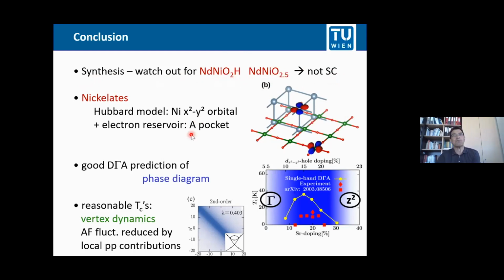Then I've shown you that for the nickelates, you can effectively describe them by a one-band Hubbard model for the nickel x squared minus y squared orbital. The A pocket is just an electron reservoir, a passive bystander that comes out from DMFT calculations with multi-orbitals taken into account. And then as a next step, at least in the blue region of doping, you are good with a one-band Hubbard model. We calculated the phase diagram, and the Tc is very good compared to experiment, even though we did the calculation before experiment.